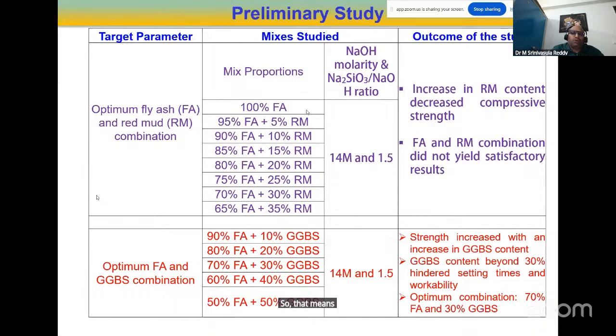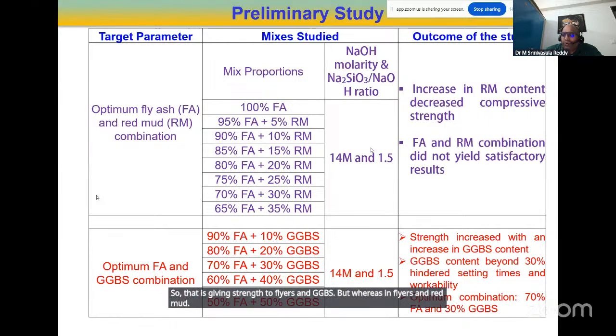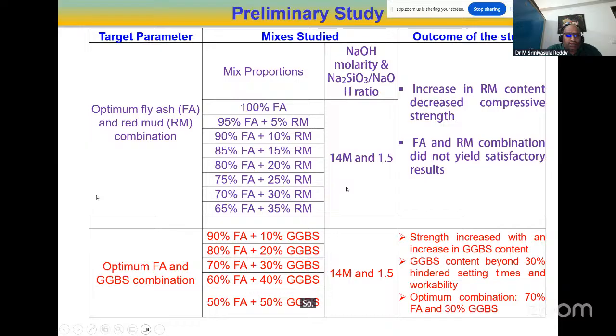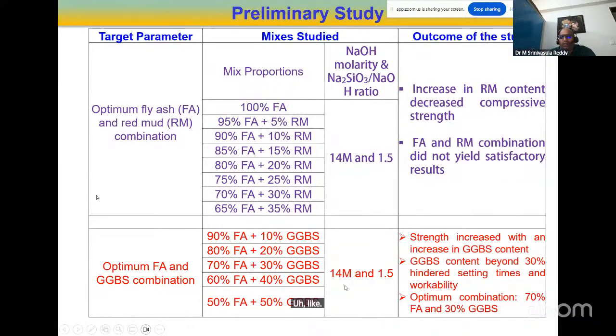So that means we cannot use these two combinations because in red mud we don't have, at least in GGBS we have, a reasonable amount of calcium oxide. Because of that, in addition to geopolymerization, we are also having C-S-H gel and C-A-S-H both. C-A-S-H is also forming. So that is giving strength to fly ash and GGBS. But in fly ash and red mud, red mud is mostly aluminum and iron oxide. So that will not contribute much to the strength of the geopolymer concrete. Because of that, with the addition of red mud to fly ash, I noticed a decrease in the strength. So we can discard this combination. We cannot go with this combination of fly ash and red mud, at least for developing geopolymer concrete.